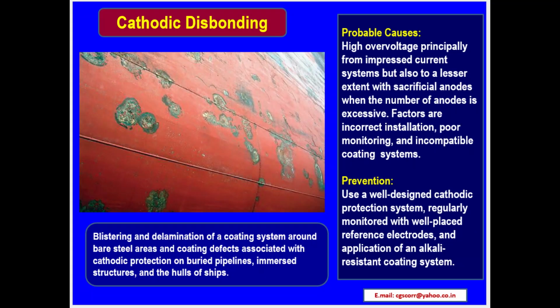The next defect is cathodic disbonding, which is described in the left side top of the screen. Blistering and delamination of a coating system around bare steel areas and coating defects associated with cathodic protection on buried pipelines, immersed structures and hulls of ships.